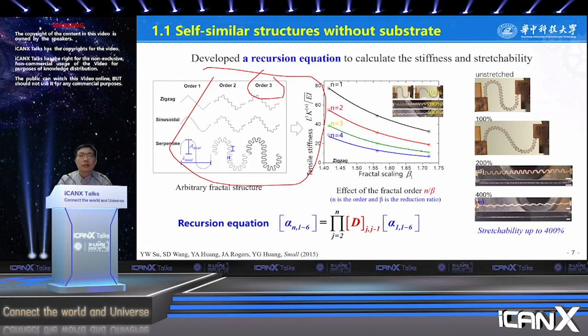The elastic stiffness of the fractal interconnects is determined analytically. The middle figure indicates the relationship between the stiffness and the orders. The normalized tensile stiffness decreases with the order number. The tensile stiffness is clearly expressed by a set of non-dimensional parameters. We fabricate a two-order self-similar structure, and it can be stretched up to 400%.